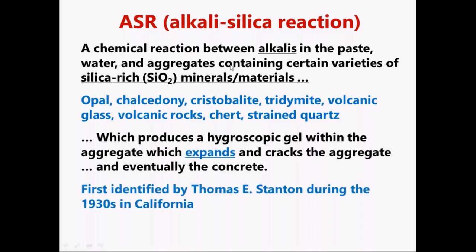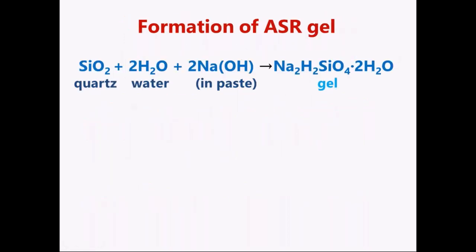What happens is that the alkali in the paste and water and silica from any one of these minerals produces a gel which expands with water. The expansion then causes the concrete to fail. ASR was first identified by Tom Stanton back in the 1930s in California, just FYI.